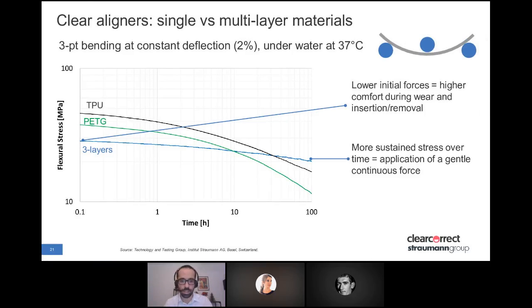So I'd like to show you here an example of our flexural stress relaxation test we did in our lab. It's a 3-point bending, a constant deflection, 2% and in water at 37 degrees. Our 3-layer material, as you can see, starts from a quite lower initial stress, but over time, it's more sustained compared to an example of a polyurethane and a PETG. So the lower initial stress is associated with a higher comfort, and the more sustained stress with a more predictable, more constant force application.